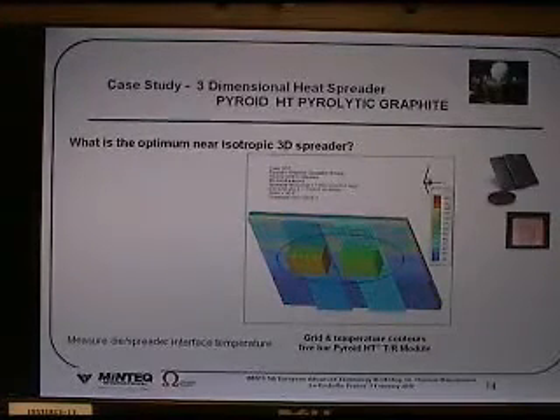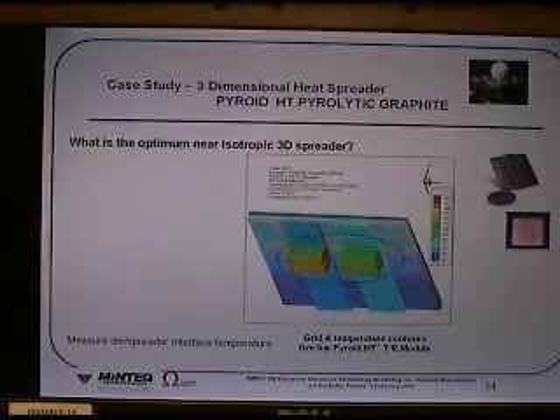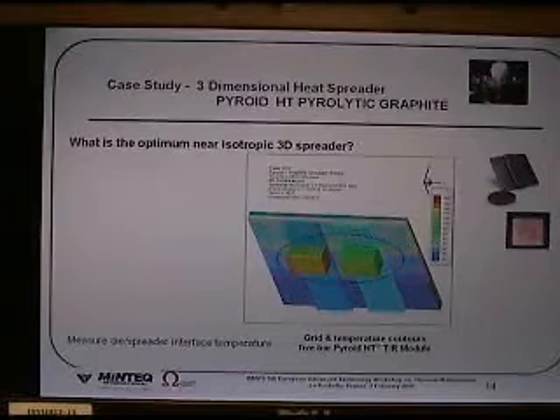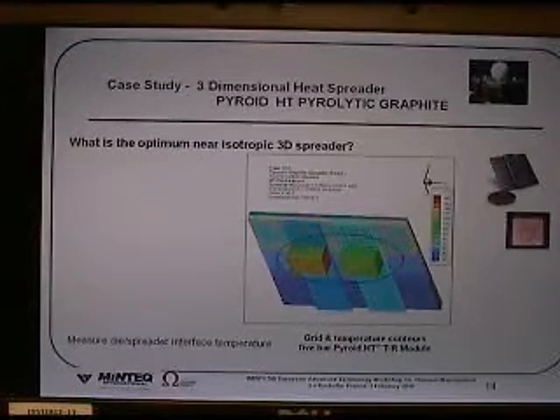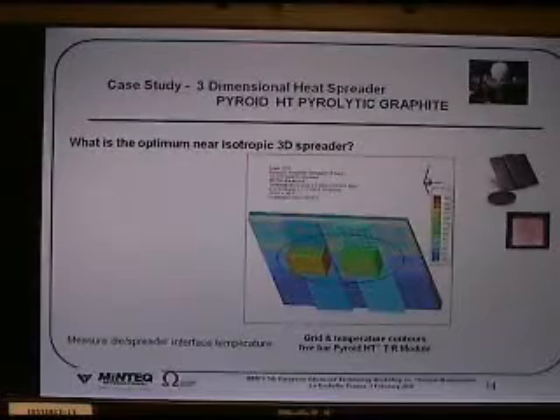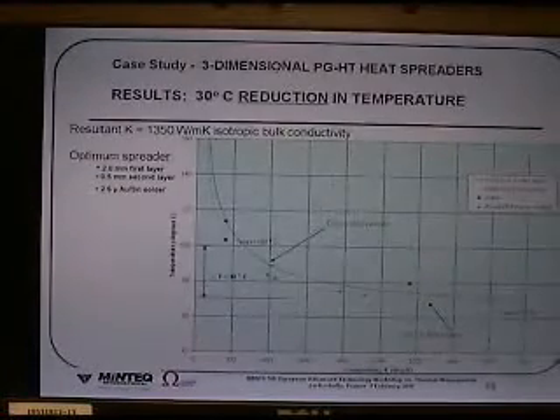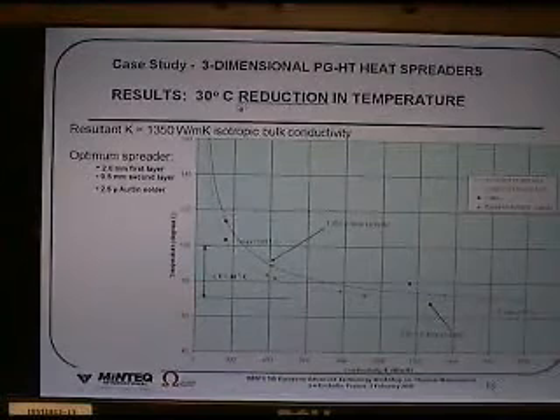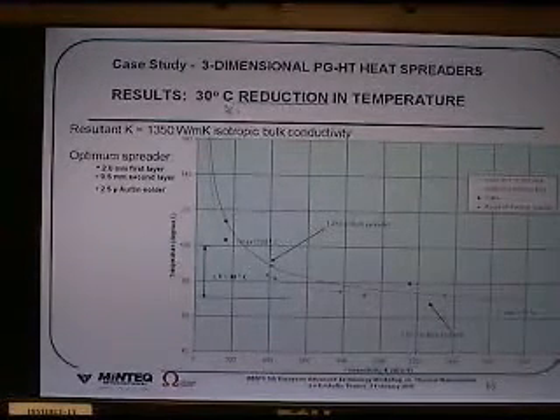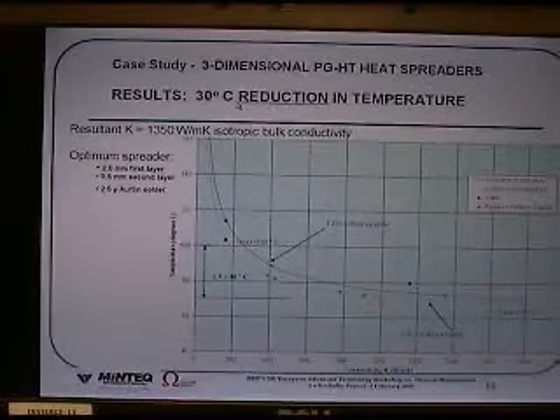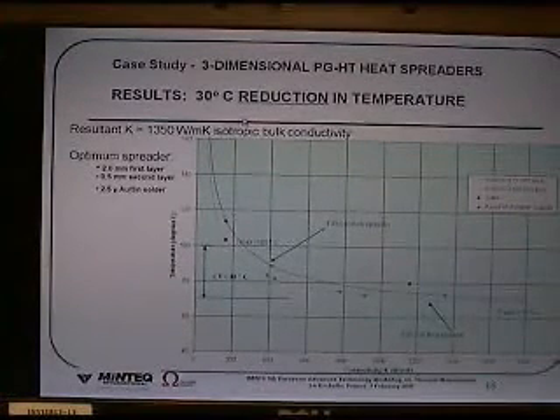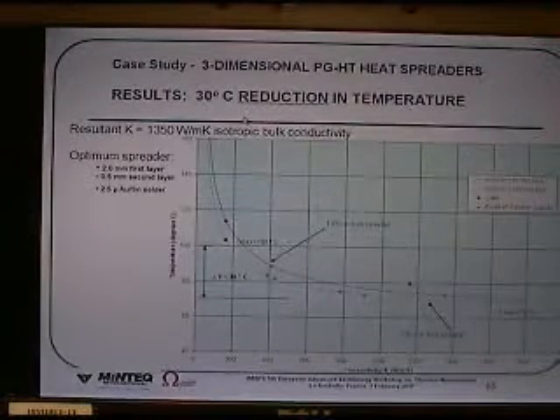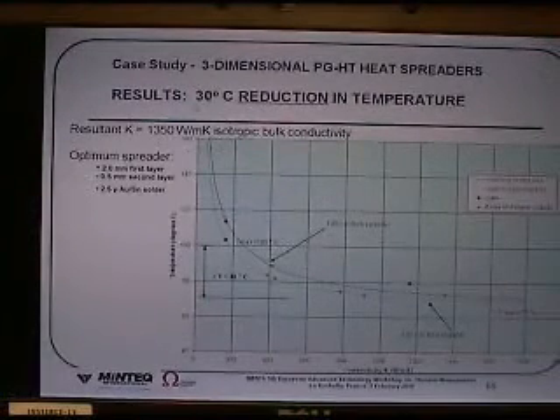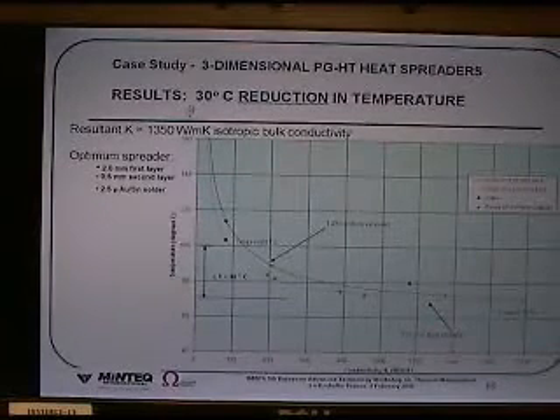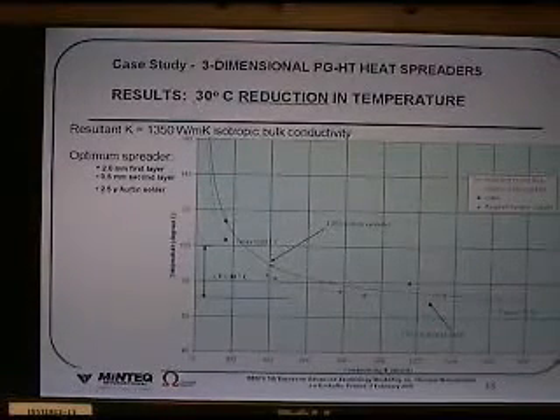We also understand that certain applications require a three-dimensional heat spreader. And because of the engineering capabilities of this material, we're able to manufacture a near isotropic three-dimensional heat spreader. And so we'll look at the results for such a case. Here, once again, we're able to enjoy over a 30 degrees centigrade reduction in junction temperature using a three-dimensional engineered layered approach, which has a resulting average isotropic bulk conductivity of 1350 watts per meter K.